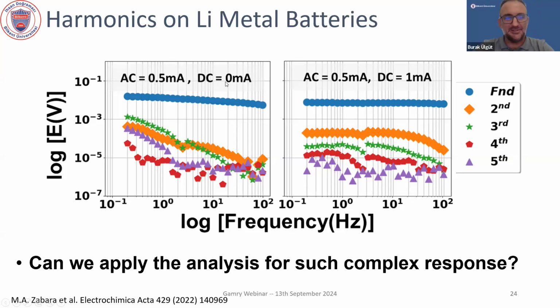But under this condition at 0 DC, we have drift issues at higher frequencies, but we have clear nonlinearity issues at lower frequencies. And it turns out the low frequency in this particular battery, which is the lithium thionyl chloride, is actually giving you information about a different process under 0 DC versus 1 milliamp DC. In 1 milliamp DC, it's really the cathodic process of thionyl chloride reduction. However, in 0 milliamps, it is the reaction that leads to the escape of SO2 that is happening on the cathodic side, because you're going between charge and discharge, which is something that you should not do on a non-rechargeable battery. So the nonlinearity here is actually telling me a lot of things about the process.